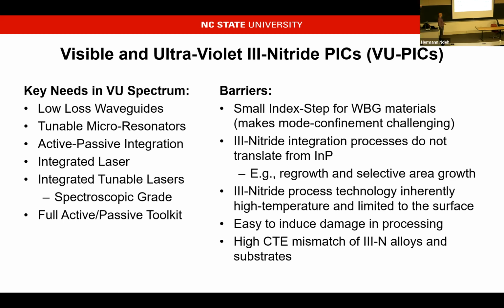Nitride process technology is inherently high temperature and limited, and because it's high temperature, it's generally limited to the surface. So trying to do deep processing, like I showed earlier on, where we're diffusing silicon a micron into a device and making a buried heterostructure laser, is not something you can readily do in the nitrides. It's also easy to introduce defects in the processing, and there's a high CTE mismatch of the alloys and the substrate. All these make things much more challenging than the nitrides, and it's why we can't just plug and play what we know in the arsenide phosphide.